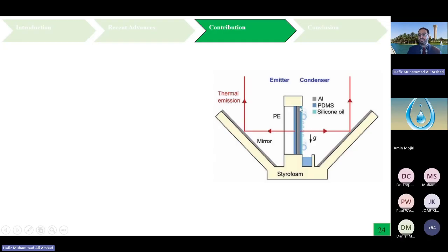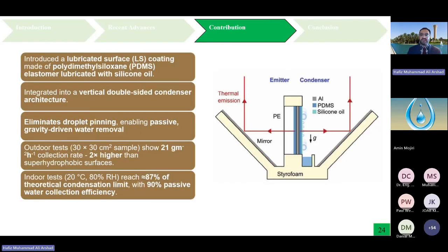On the other side, there is a combination of PDMS, aluminium, and then silicone oil. It also provides cooling, but at the same time, when water touched that surface, it condensed, and we had water collection. So we did some outdoor testing on a smaller sample, which was 30 by 30 centimeters square.